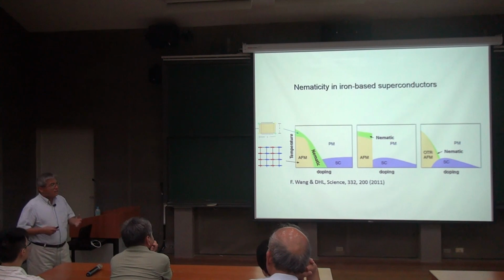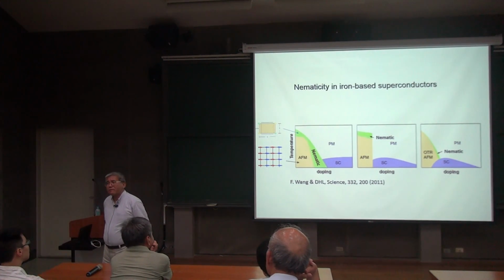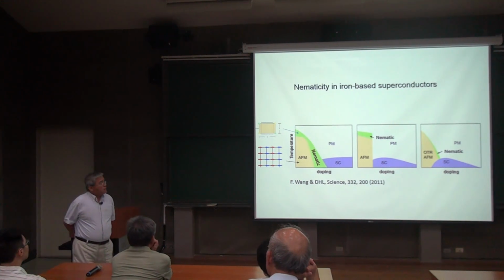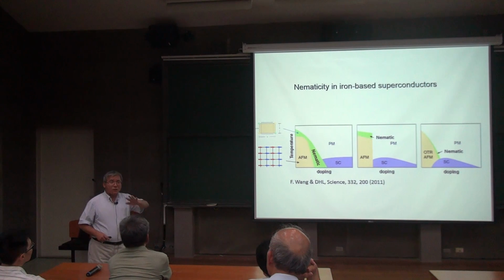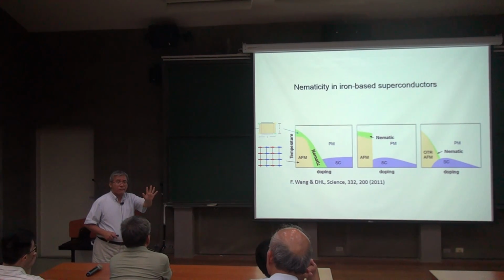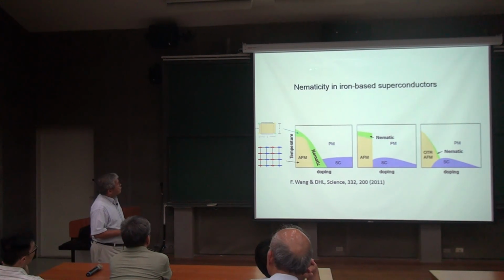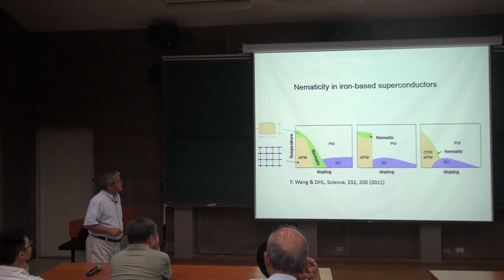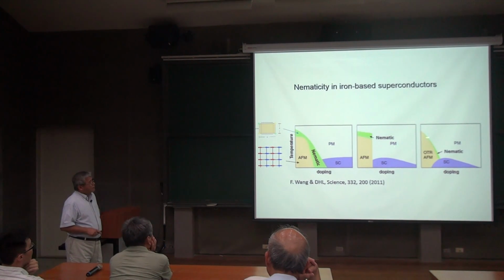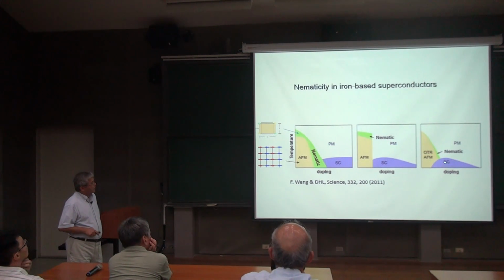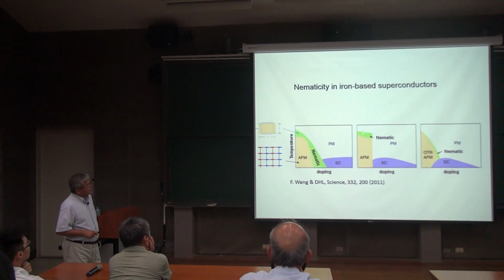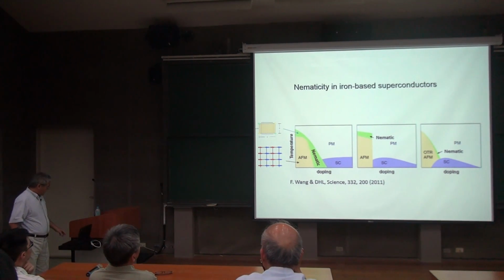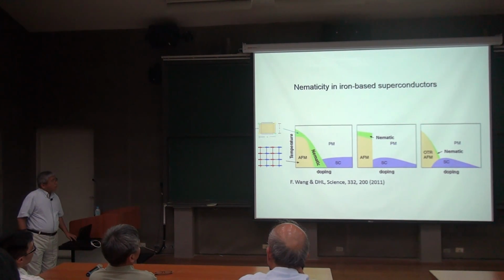And this nematic state is a phrase borrowed from the study of liquid crystals, and it means a state without translation symmetry breaking, but with rotation symmetry breaking. So this is what we mean by nematicity in iron-based superconductors. As you can see, for all different types of iron-based superconductors, they all have three different phases, namely the antiferromagnetic phase, the green region, which is the nematic phase, and then the superconducting phase. The main message of this slide is that the nematic phase is ubiquitous. It's not an exception, but a rule in iron-based superconductors.